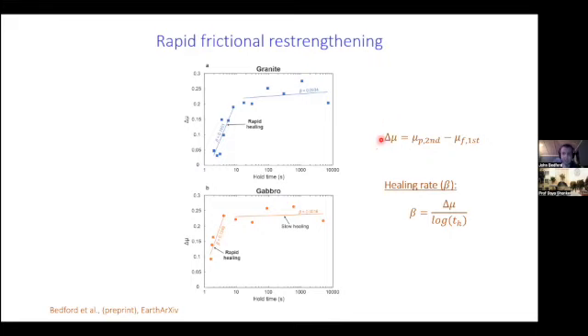So we're looking at this difference here and plotting it against the hold time, and that's what these graphs are showing here. This delta mu is the peak friction of the second sliding event minus the final steady state friction of the first sliding event. And you can see that both materials, the granite and the gabbro, actually recover their strength very rapidly. So that 0.25 that was lost during the first sliding event is recovered in about 20 seconds for granite, and for gabbro it's even faster, maybe less than 10 seconds. It's recovered almost all the strength that it lost during the first sliding event.